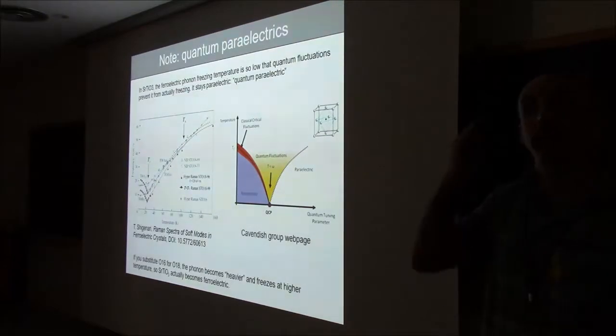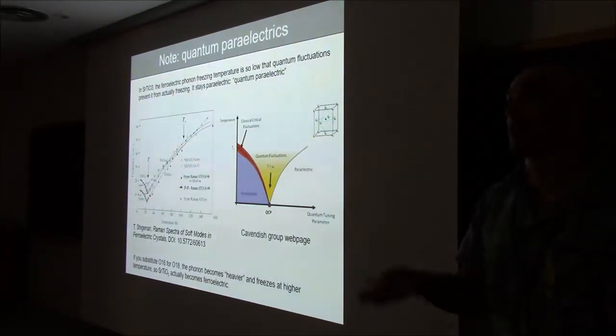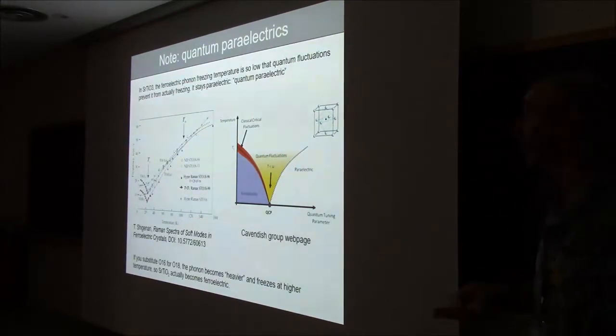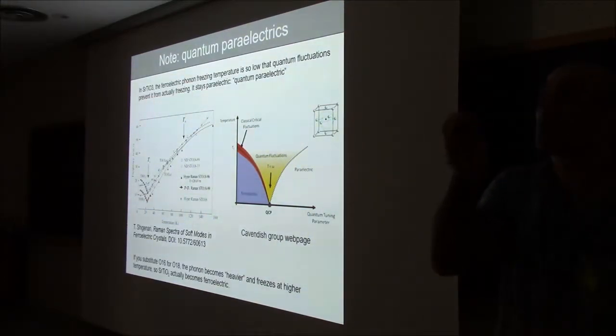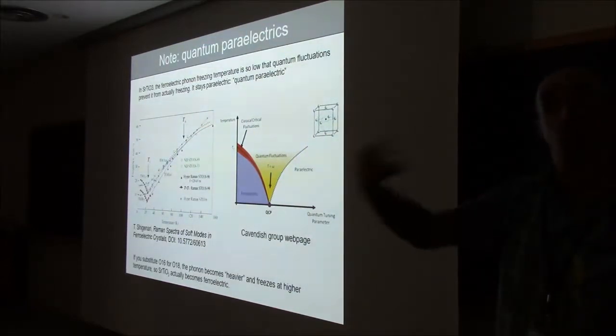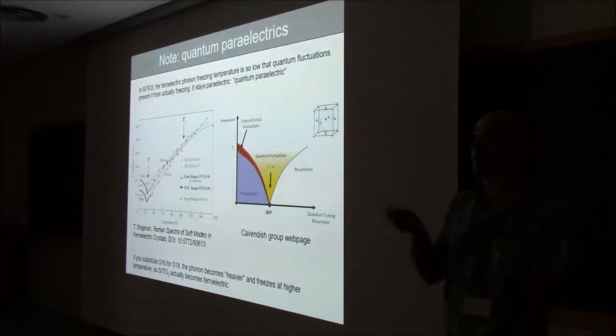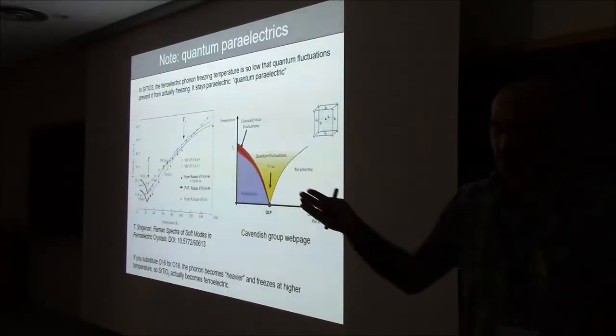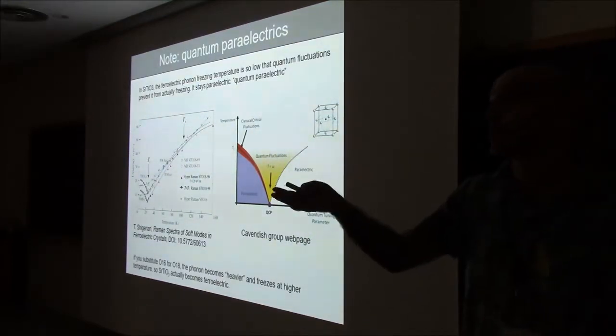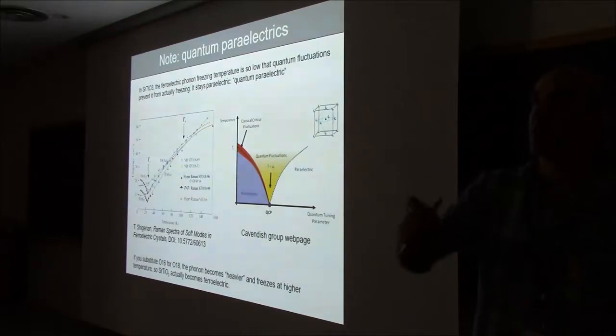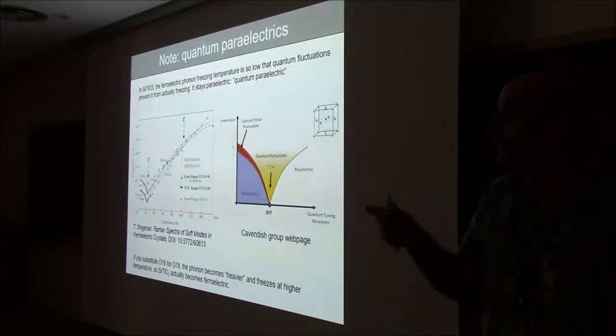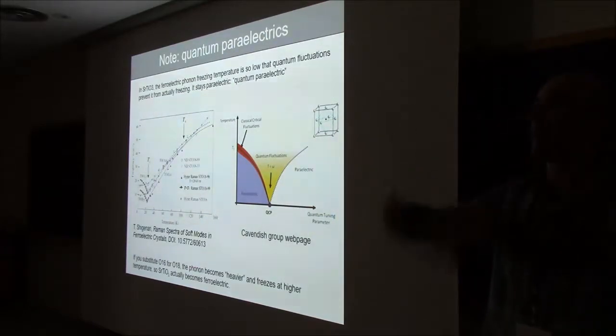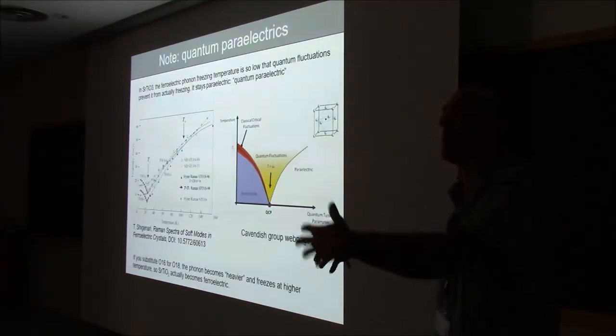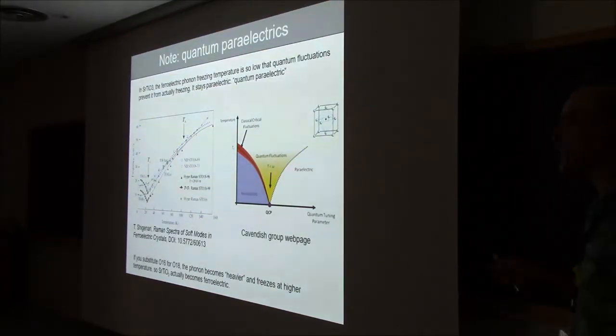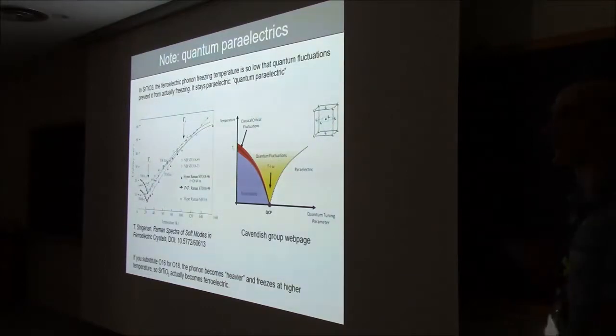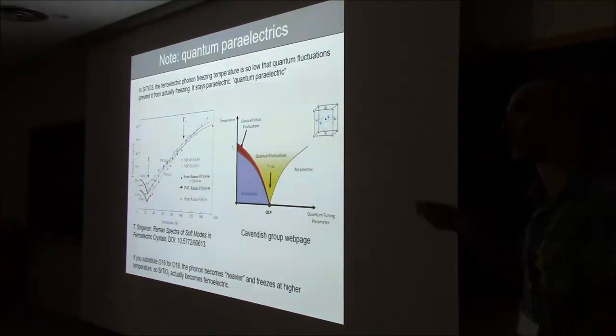And that's what happens in a material that is probably very familiar to you, which is strontium titanate. Strontium titanate would like to be ferroelectric, but it just so happens that its ferroelectric critical temperature is so close to 0 that the phonon cannot freeze due to quantum fluctuation. Now there's this very exciting experiment whereby you can substitute the oxygen atoms in your STO by oxygen 18. So instead of oxygen 16, you use oxygen 18. Oxygen 18 is heavier, and because it's heavier, the phonon freezing happens at higher temperatures, so it can actually freeze before it enters the quantum region. So just by changing the weight of the oxygen, you can turn something from being paraelectric, actually a quantum paraelectric, into being ferroelectric.